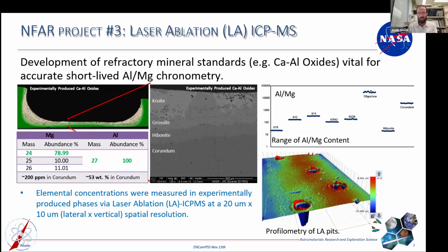With the laser, we do have that sensitivity, and we were able to come up with a technique that allowed us to measure both the aluminum and the magnesium in situ for a series of experiments on these refractory phases, these ceramics. Corundum is maybe something people are familiar with, but then there's hibonite, grossite, and krotite, which are various versions of calcium aluminum oxides that are found in the natural samples. We can calibrate these standards and then use them to calibrate our other in situ measurements and get presumably accurate ages. So that's really highlighting the laser ablation capability.